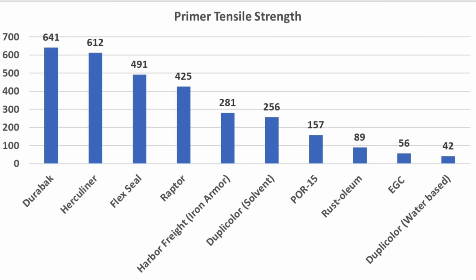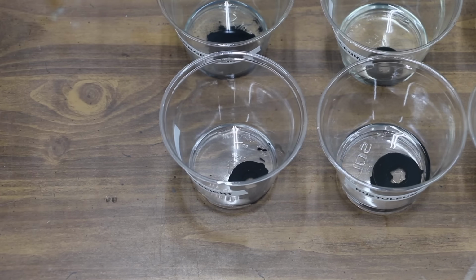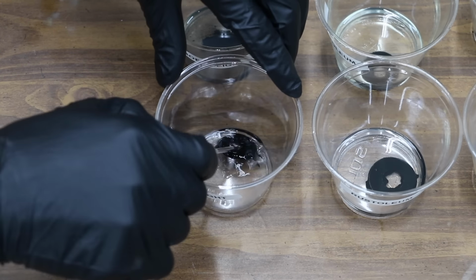A poor bonding product is more likely to flake away around damaged areas compared to a bedliner with strong bond characteristics. Durabak did by far the best, Herculiner second, Flex Seal third, Raptor fourth, and Iron Armor fifth. It's been right at 90 minutes since the bedliners were exposed to rubbing alcohol, non-ethanol gasoline, and diesel.